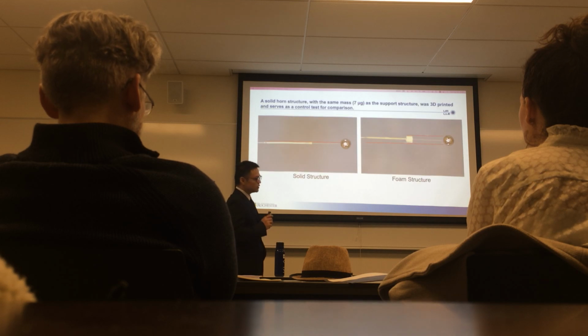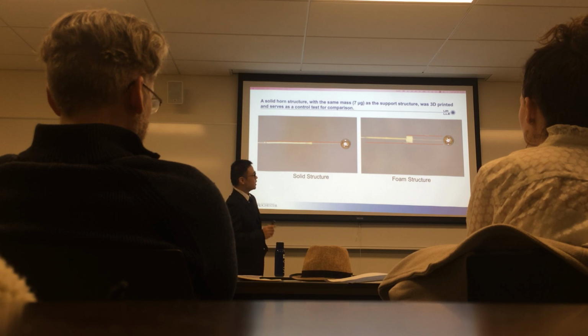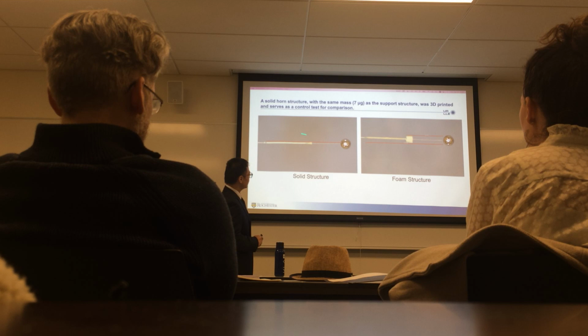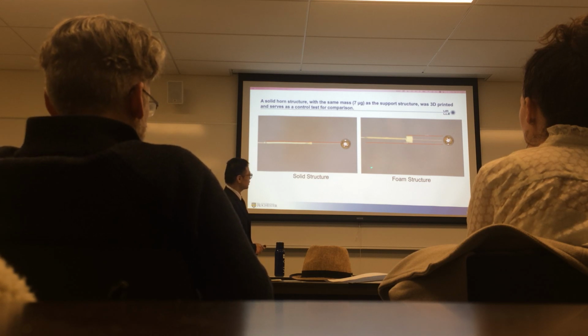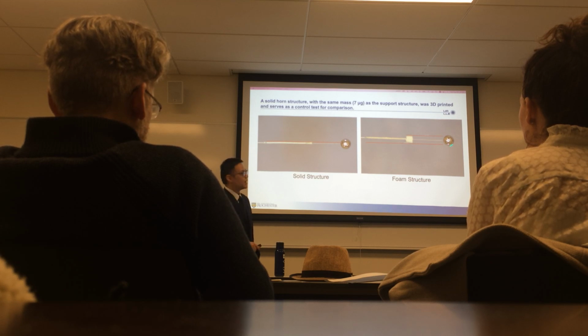Okay, we do not just use the empty target structure as our control group. We also use a solid structure as our control. The solid structure only differs from the foam structure in that we use a solid part to replace the foam part. And this solid part has the same mass as the foam structures. The reason I want to use the solid part is that we want to exclude the materials' influence. We want to make sure these structures dissipate energies, not the materials.